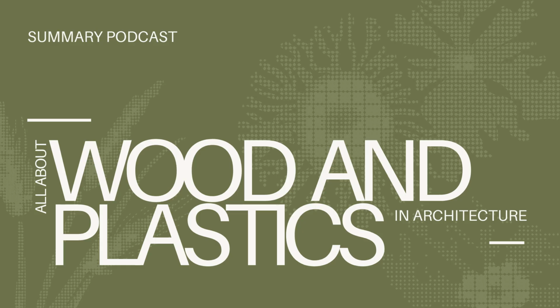And there are different types: standard, panel, and tempered. What's the difference? They vary in density and durability. Standard hardboard, light brown, fairly hard, flexible, good for general interior use where it won't get wet. Panel hardboard, denser than standard, a bit tougher. A middle ground. Tempered hardboard. This is the toughest type. It's standard hardboard that's been impregnated with oils and resins and then baked. This makes it much denser, harder, stiffer, darker brown, and significantly more resistant to moisture and abrasion. So tempered is the one for exterior use or wet areas. Exactly. Ideal for exterior siding components, soffits, or even bathroom linings where moisture resistance is key.